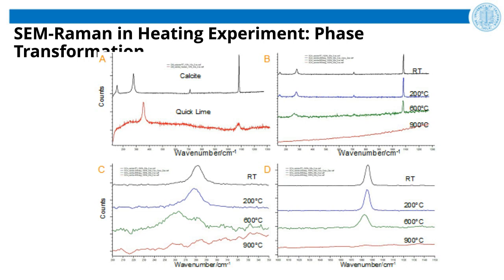In these high zoom spectra, we can see a slight shift of the peaks, and we also can see the split of the peak at 280.